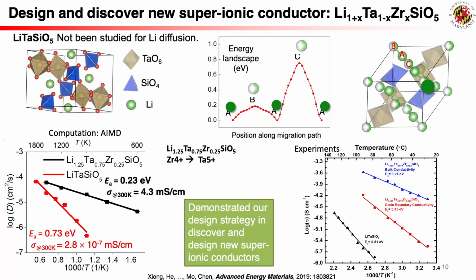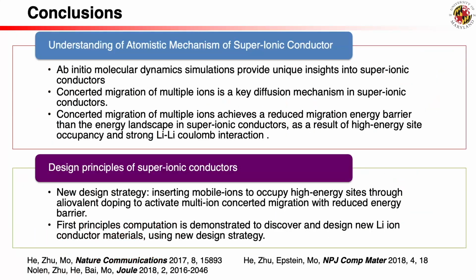So to recap, fast ion diffusion in SICs is mainly due to this concerted migration of multiple ions. It's a team effort. And this is facilitated by the way ions occupy high-energy sites, and those strong Coulomb interactions. Right, and the flat energy landscape at those sites. All working together. And this gives us a new way to design better SICs. A more rational approach. This has been a great deep dive.